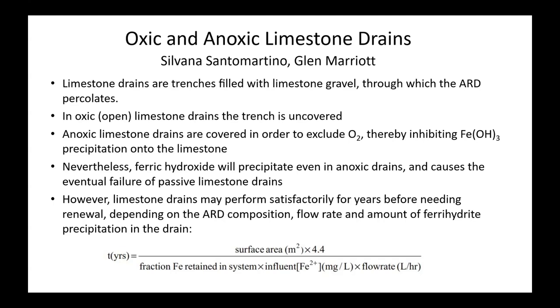However, when these were first developed, there were high hopes for them, but alas, they all failed because you just can't stop that ferric hydroxide precipitation. So inevitably, limestone drains will fail, no matter how much you try to exclude the oxygen. However, they can perform satisfactorily for years before they fail. And Silvana developed an equation that is a rule of thumb, really, showing that depending on how much iron's going into them, how much is retained, how big they are, and how much water's flowing through, they can last for years. And they just need monitoring.